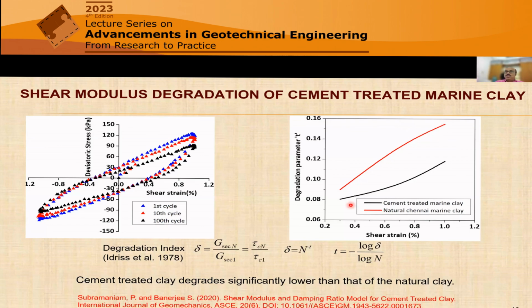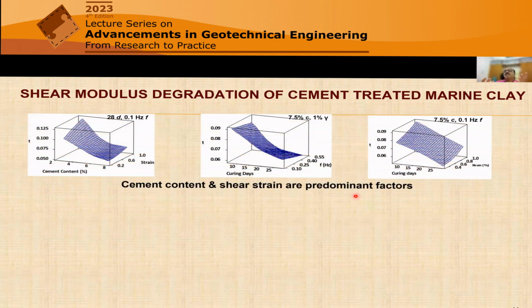But obviously in cement treatment, you see a reduction in the degradation behavior, but it's not ignorable. I would say it's not completely negligible. It is also showing very significant degradation even in the cement treated soil. So the assumption that cement treatment is a cure for all may not be the correct one. Because it's a multiple-factor problem, you cannot really attack one of the parameters. You have to see multiple facets of this behavior.